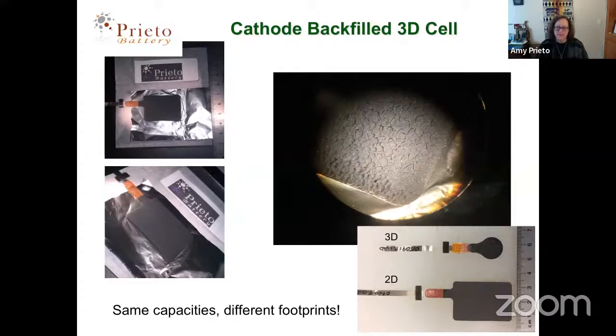But what's really amazing is I'm going to show you some data in a moment comparing the 3D architecture to the 2D architecture. And it's really important to be able to compare apples to apples. So what we want to be able to do is compare this 3D battery to a 2D battery made on copper foil, but made with the exact same process, the exact same materials, and importantly, the exact same capacities. And so what I'm showing you in the picture on the bottom right is a 2D battery on copper foil, but the exact same materials, copper antimonide, electroplated polymer, spray-coated cathode, and then the 3D battery on the top.